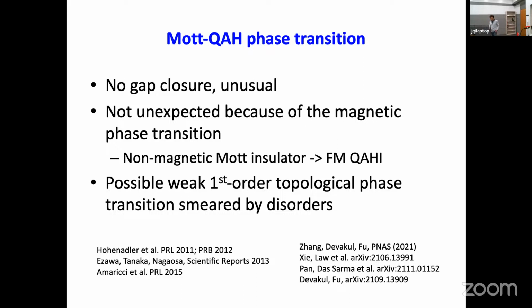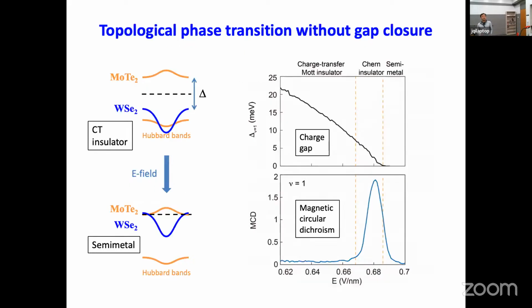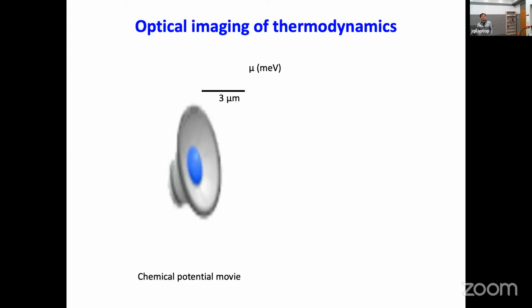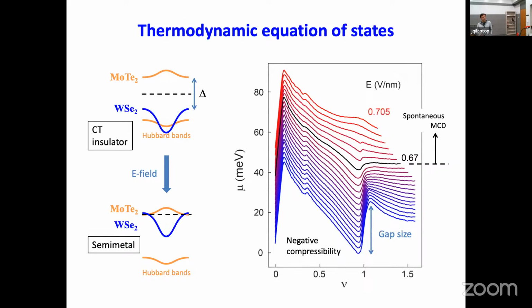Okay. I have an experimental question. What is the material used for the sensor? I'm assuming it's a different temperature, have a different. Actually, we used a tungsten selenide as a sensor also. The reason is that once the tungsten selenide is in proximity touch with the Moiré layer forming a Moiré period, its resonance already shifts to lower energy. So even if we use a monolayer tungsten selenide sensor, it's totally fine.